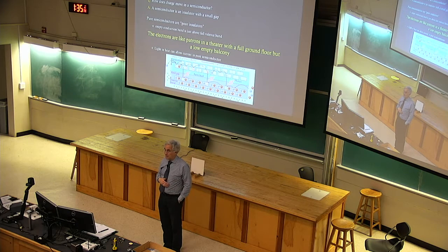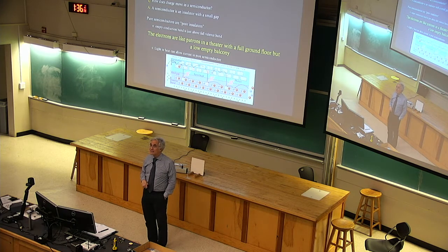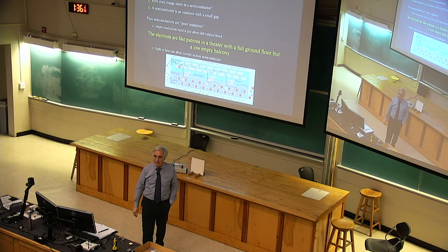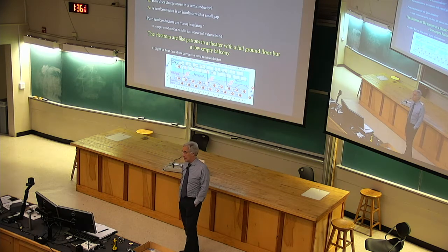So silicon has become the workhorse for most electronics. And silicon is technically an insulator, but you can get it to start conducting electricity in two ways, one more interesting than the other. One way is to heat the stuff. Hot silicon has extra energy in it, and there is often enough energy in hot silicon. I don't know how hot is hot, you put it in the oven. There's enough energy around thermally to toss electrons up into the conduction levels.